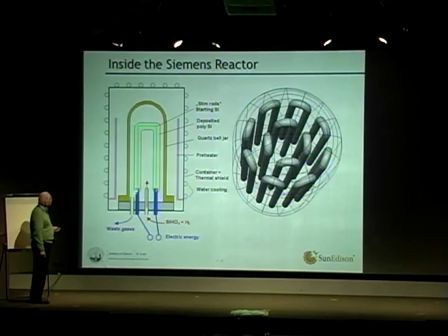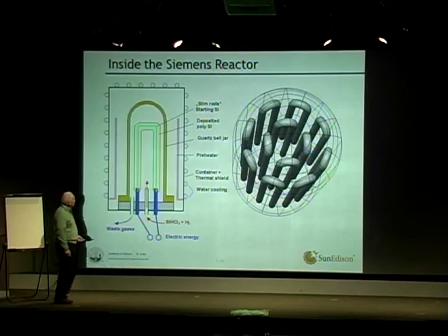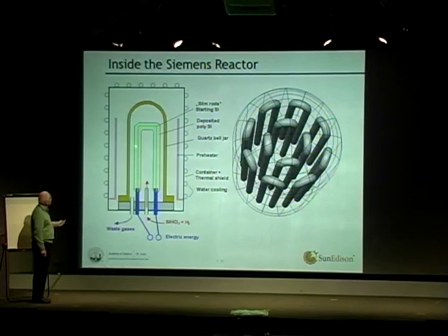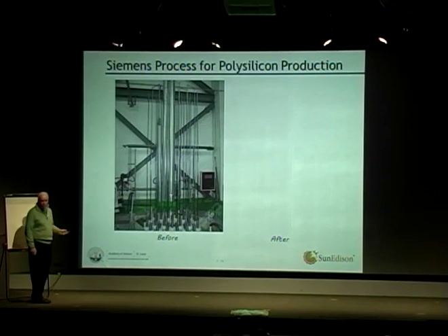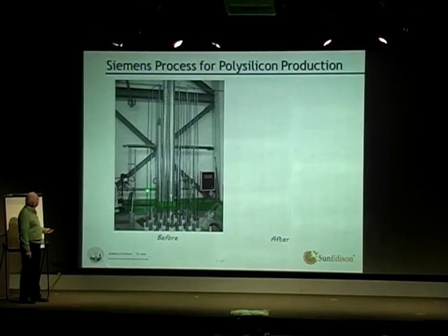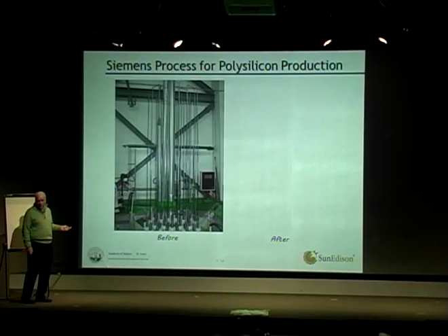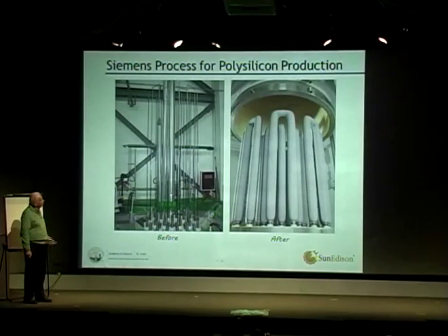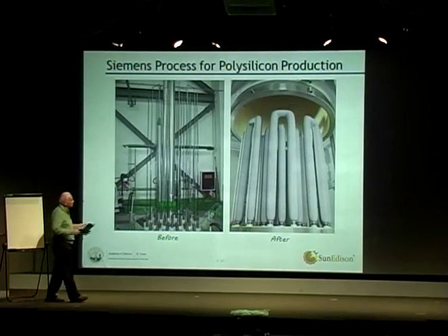Here I only show one simple inverted U, but in fact, there are lots of them inside a reactor. So what happens is, here's the slim rod. Let me go to the next thing. I don't know if you can see this too well at the back, but here is the slim rod going up, then going across the top and coming back down. It completes the electric circuit, so that heats it up. Then as you put the trichlorosilane in gas form, it deposits onto this slim rod and grows outwards and you end up with this. Okay, so it becomes fatter and fatter.